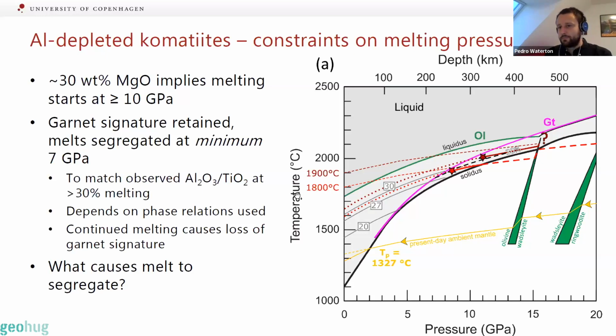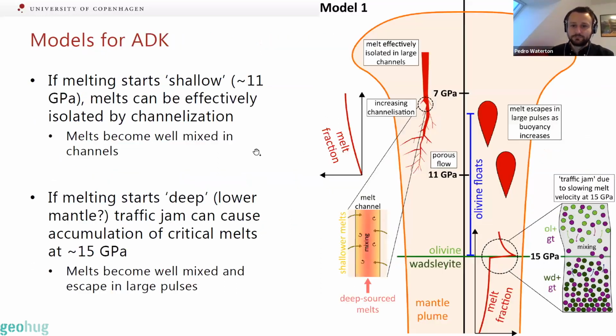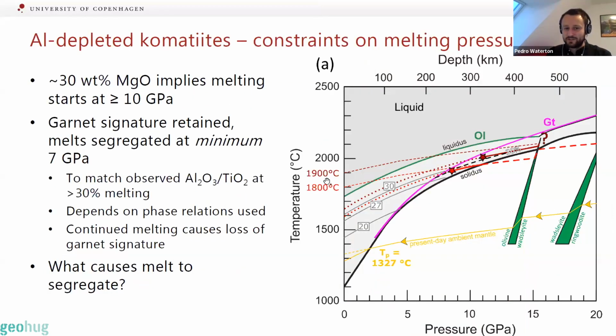So what causes the melt to segregate? And bear in mind, we need the melt to remain quite isolated from the surrounding mantle, because otherwise further melting will introduce melts which don't have this garnet signature and erase it from our aluminium depleted komatiites. So we came up with a couple of models for this. The first one is this shallow, still really deep, but shallow melting model, where melting starts around 11 gigapascals, corresponding to the 1800 degrees C potential temperature in this figure.